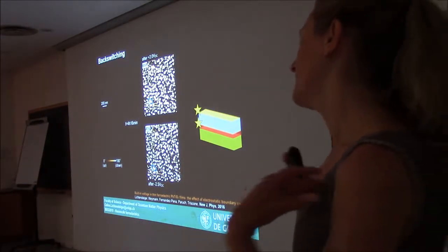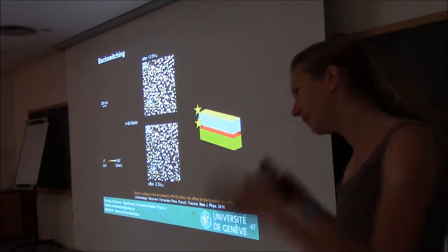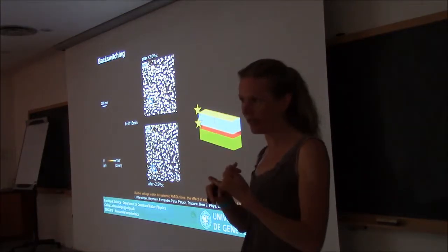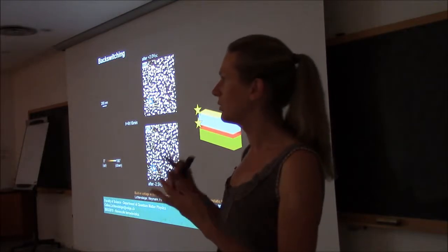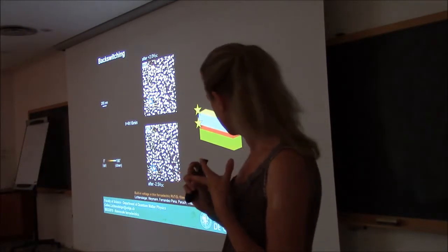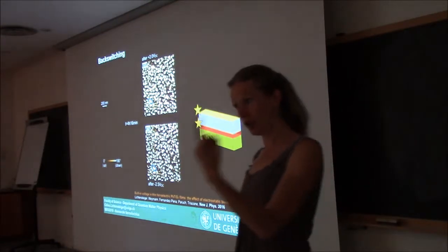Yes and no. What we've seen in the past is that for a specific set of growth parameters, if you change the bottom electrode, for example Nb-doped STO, strontium titanate, we did LSMO as well, depending on the kind of electrode, you can have a favored up or a favored down polarization.